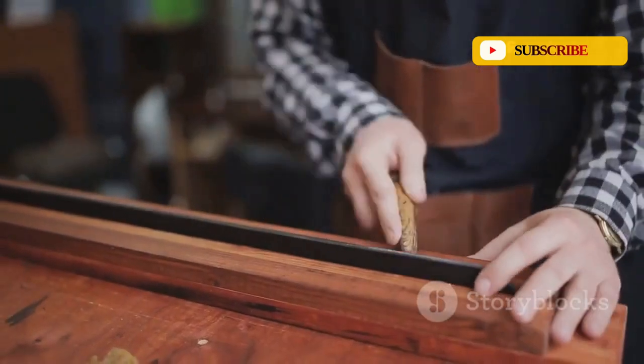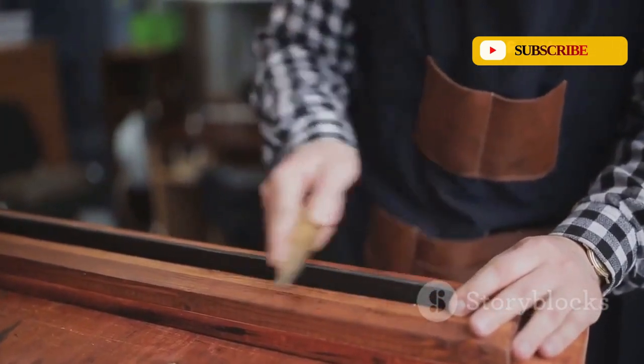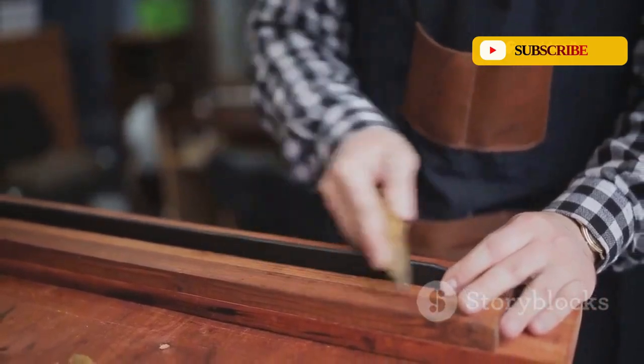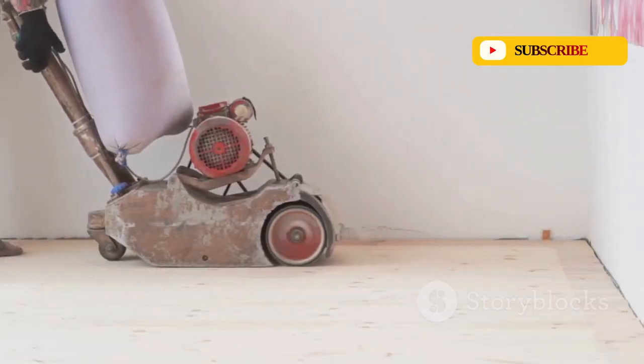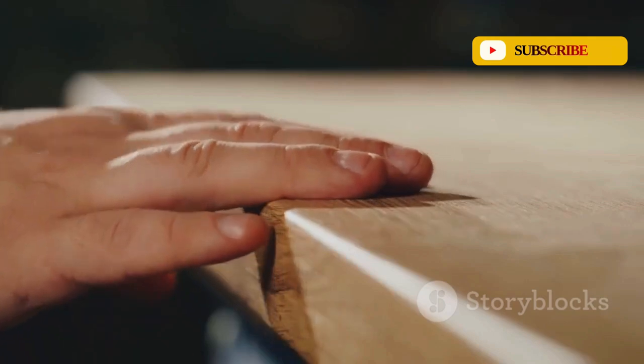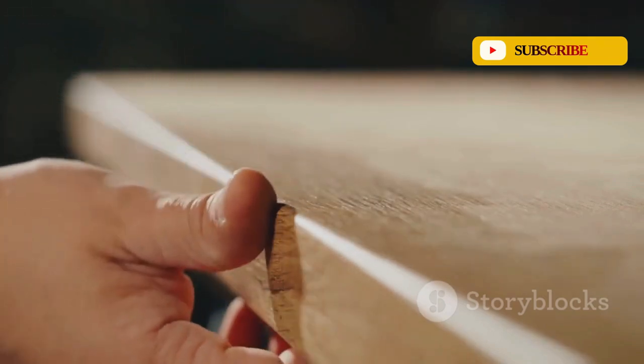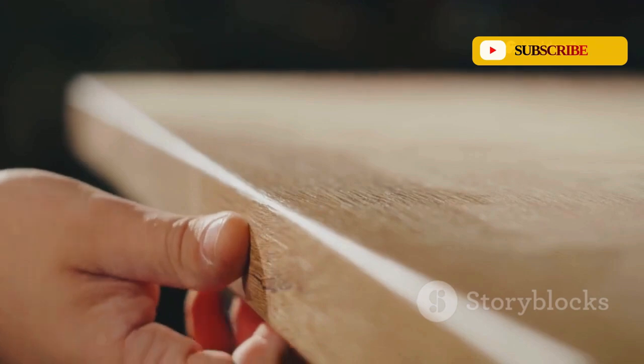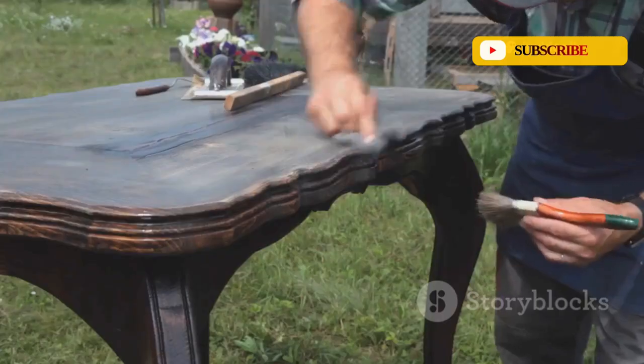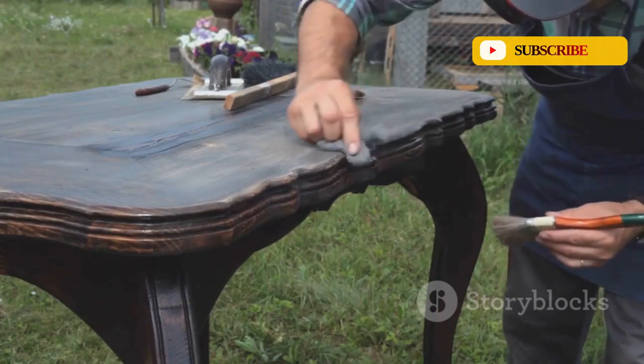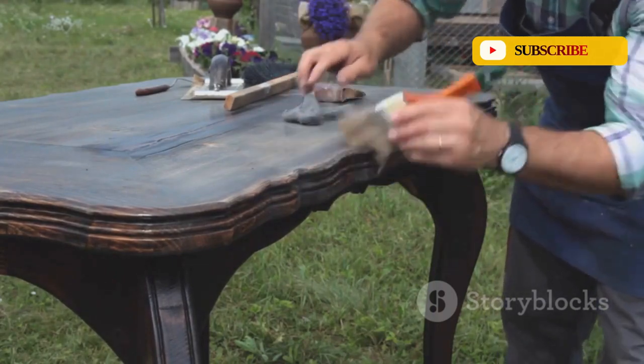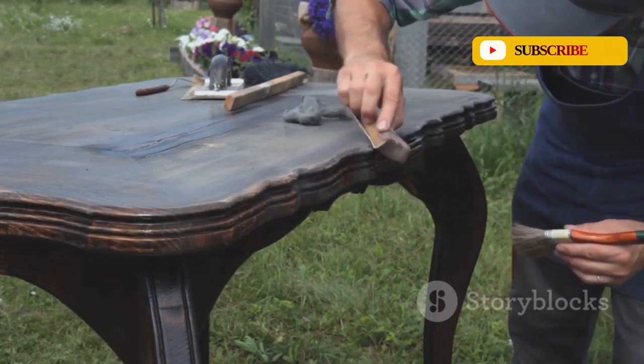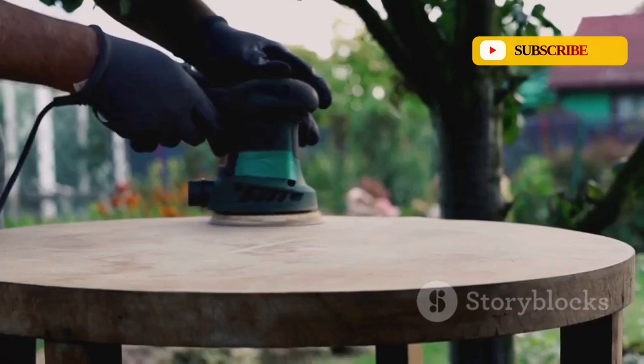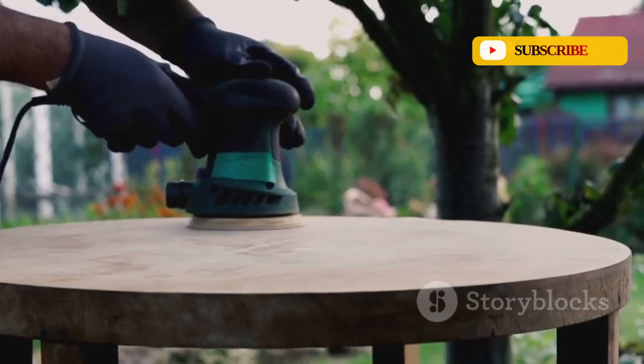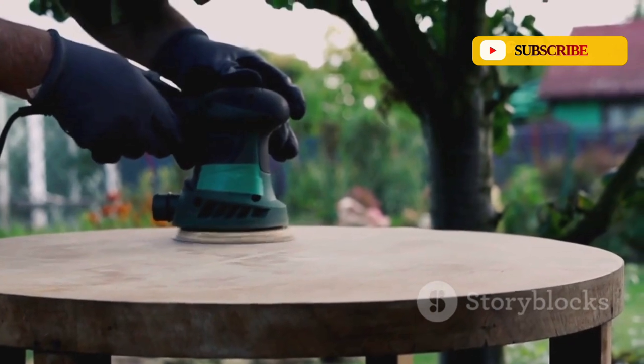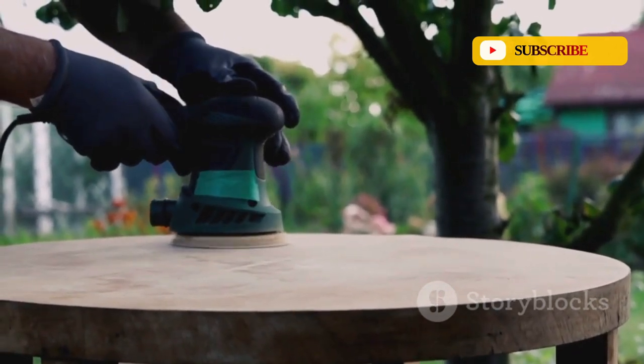Should a deep scratch or a stubborn stain ever occur on my oiled table, the repair is a simple, localized affair. There is no need for chemical strippers or a drum sander. I can simply take a bit of fine grit sandpaper, lightly sand the affected area, and reapply a small amount of my oil blend. In a day or two, the repair will be virtually invisible, blending seamlessly with the surrounding finish. Try that with polyurethane. You can't. A scratch in plastic is forever, and the only true fix is to strip the entire surface and start from scratch, a miserable and dusty undertaking.